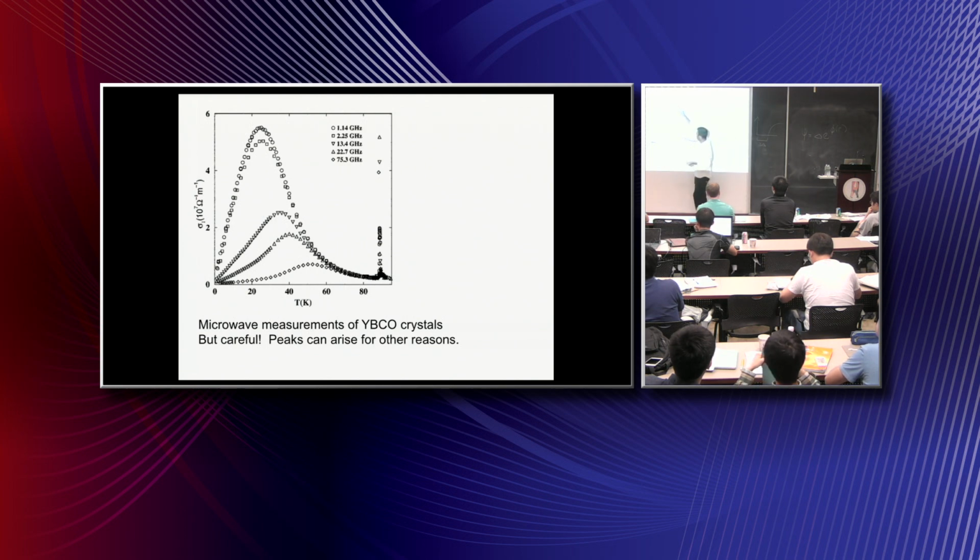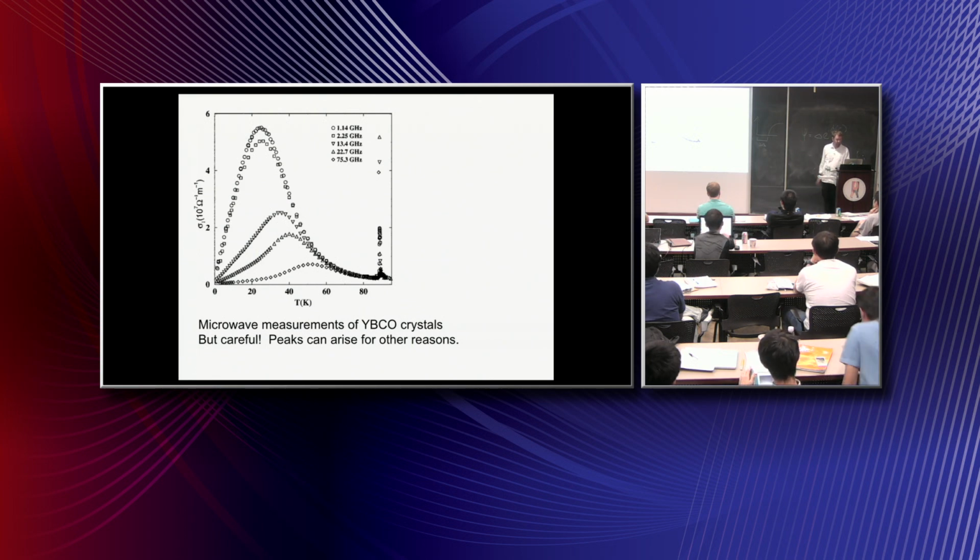This huge whopping peak down at low temperatures has to do with the d-wave superconductivity found in the cuprates. Because there are certain places in momentum space where the gap disappears, there are low-energy quasi-particles, and these quasi-particles, even though the system is superconducting, can dissipate energy at finite frequency, and they form these very, very large peaks here. This is a d-wave superconductor, and it was early evidence for YBCO not being s-wave that it had no Hebel-Slichter style peak. The nature of the coherence factors is different in this system, so it doesn't show that, but it still shows these peaks.